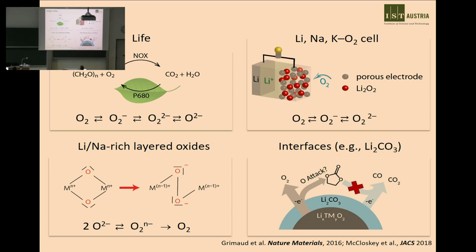And if it's there, if it's thin enough, it can pass lithium ions through it. But if you charge, and this depends on the material, if you need to charge it higher than the thermodynamic stability of this, then you're also exchanging electrons on the oxygen in the carbonate. So this would be hidden oxygen electrochemistry.